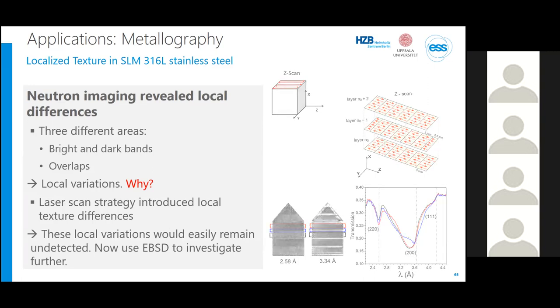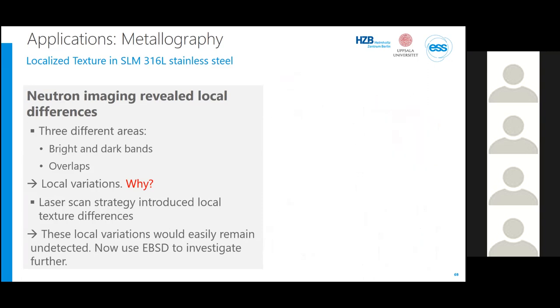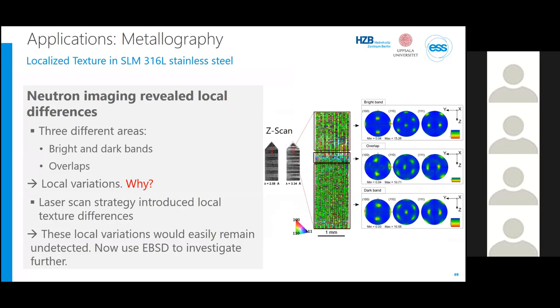And using now electron backscatter diffraction, think about the picture I showed you in the beginning of the elephant again, to really complement the picture and understand what's going on. We now see that the grains inside these different bands have a slightly different orientation and also a slightly different sharpness of the texture. And this we were able to reveal with EBSD and relate this to the neutron results.